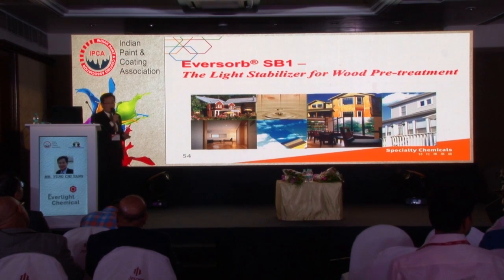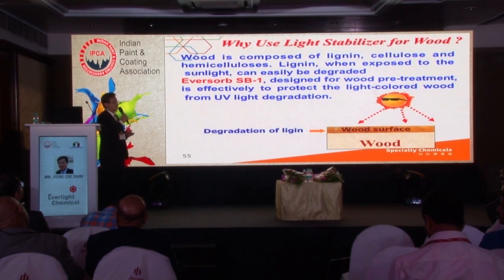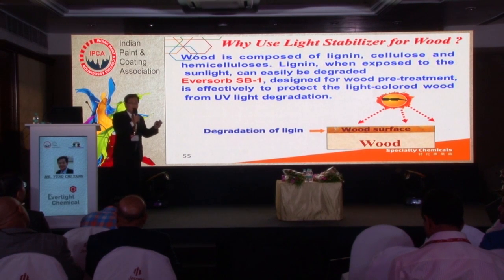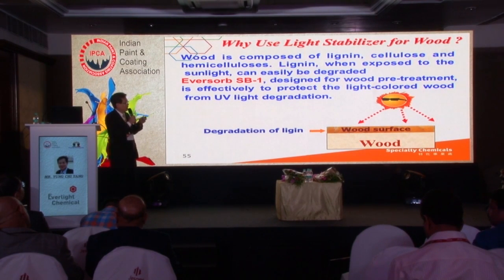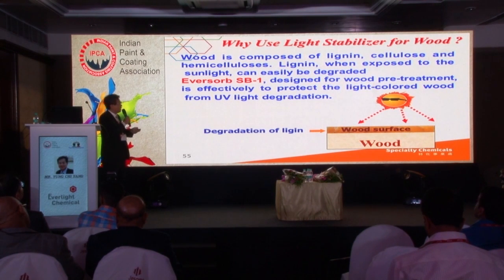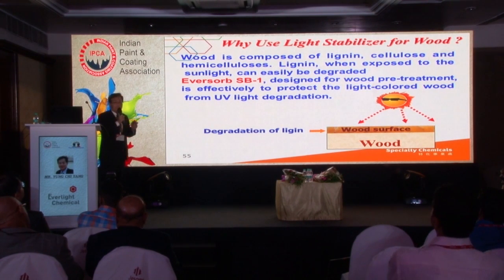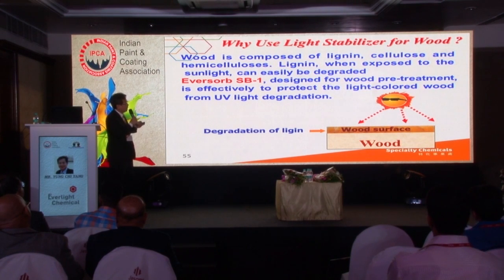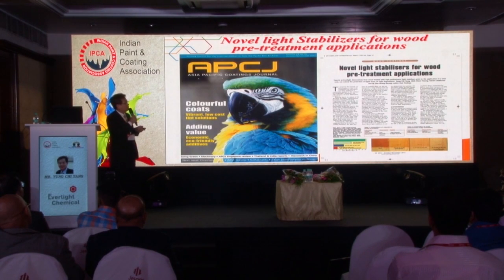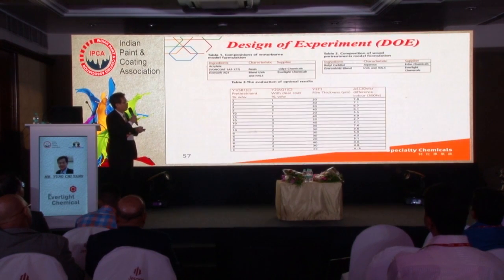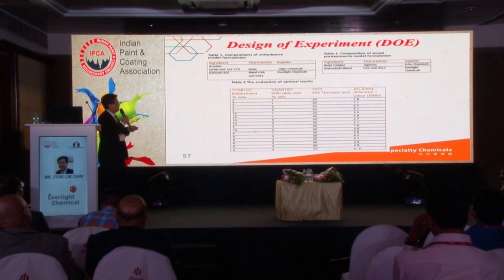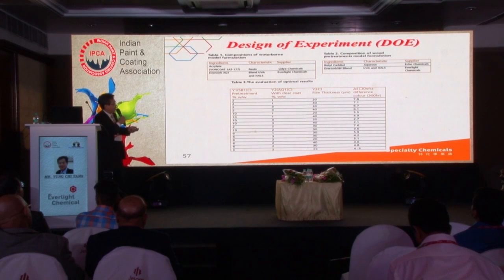The wood pretreatment is very interesting, because when the customer applies the coating on the wood surface, the coating does not degrade, but the wood does, the lignin. We find the lignin is very easy to degrade because lignin has many chromophores, so it's easy for color change and degradation. So this is very interesting, according to our research. From the different samples, you can see the SB1 is for wood pretreatment, the AQ1 is for waterborne clear coating, and film thickness, with different dosage.